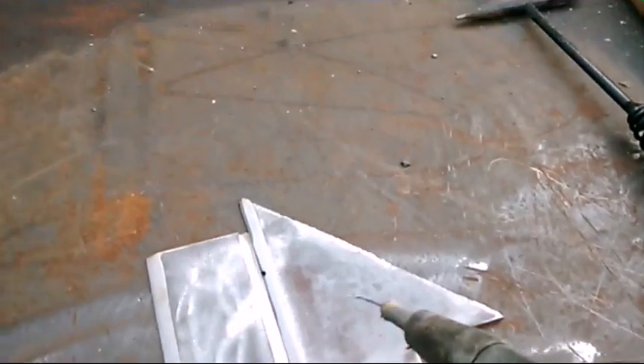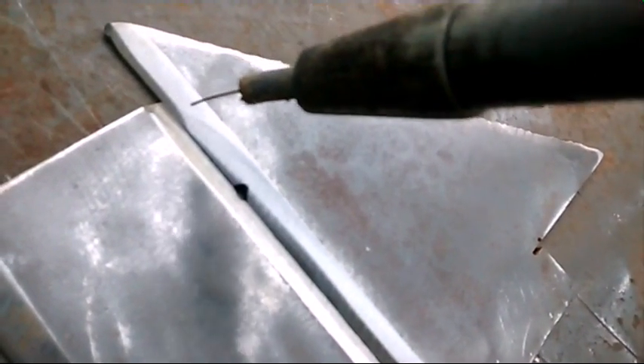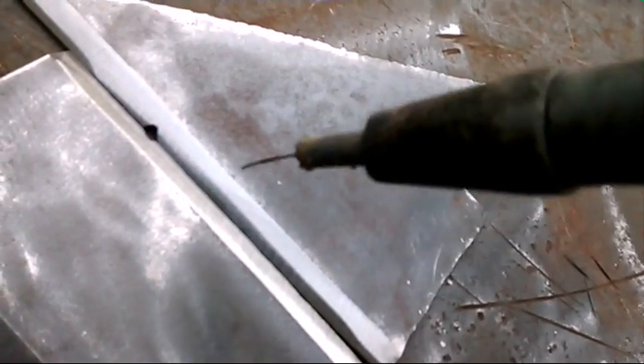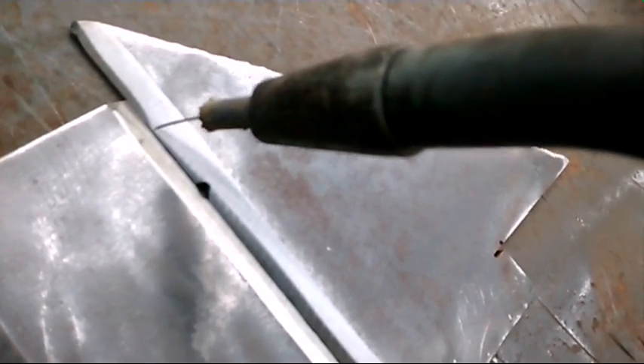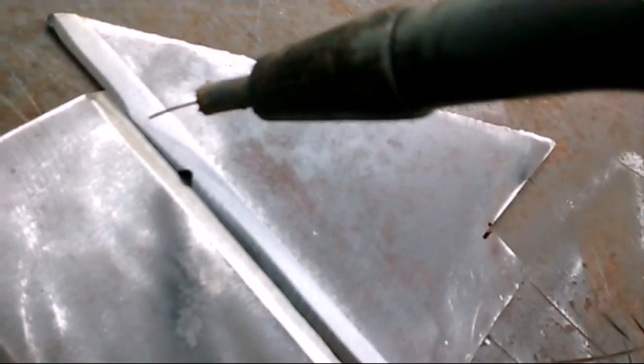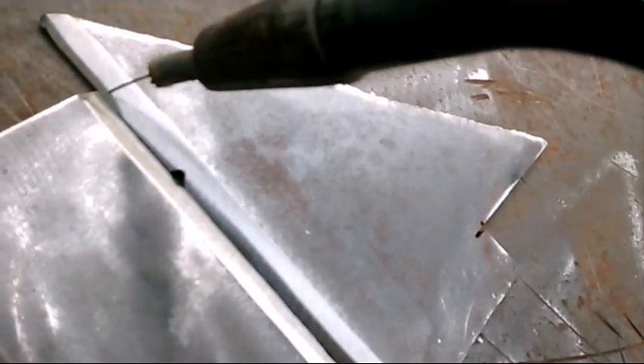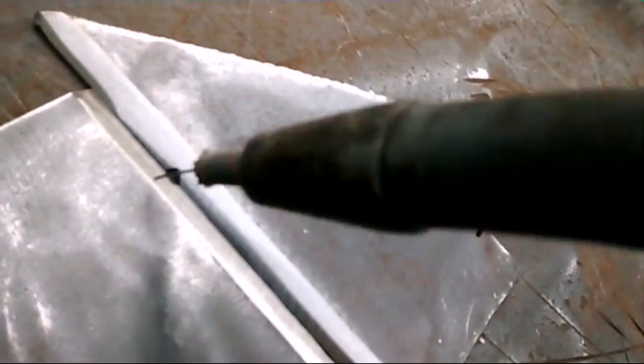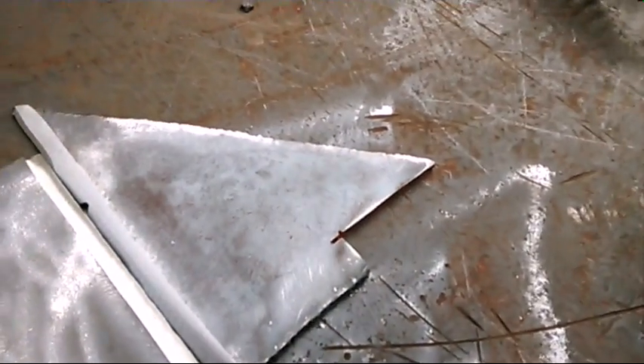And typically with this, because it has a slag in it, you're going to want to drag that thing. Because if you're pulling it behind, you could be pushing that slag back into your weld. So you kind of want to drag it at all times. Sometimes you just can't, you know. But that would be the typical thing. Held at about a 45 degree angle, just pulling it back. I go side to side slightly, depending on what I'm doing. I may just drag a root in there real quick. I blew a piece out right there, so I may run a tack right there first. But anyway, we'll get going with that right quick.